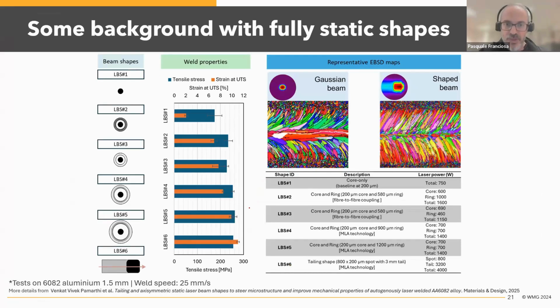Now, beam shaping. We have been researching static beam shaping for some time, doing different testing and different trials. You can see the schematics of some of the shapes we have been using, starting from a single core, then core plus ring with different diameters, and then even a tailored beam profile. All those shapes are static, but you can see the trends in mechanical performance, so tensile stress. There is approximately a 20% increase in strength when you go from a single spot to a tailored beam profile. All those welds have been made with the same processing speed, 25 millimeters a second, on the same material and the same thickness.